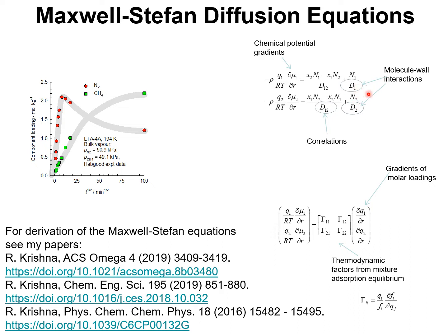D1 and D2 reflect the molecule-wall interactions, and there is another diffusivity D12 that quantifies correlations in molecular jumps within the microporous material.